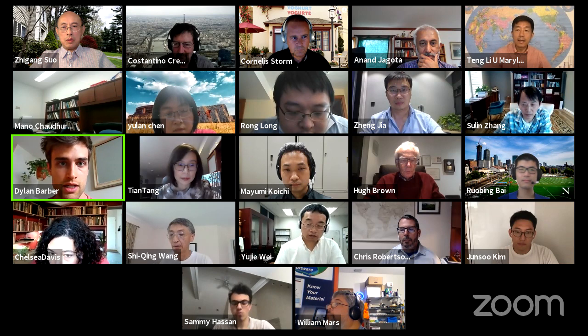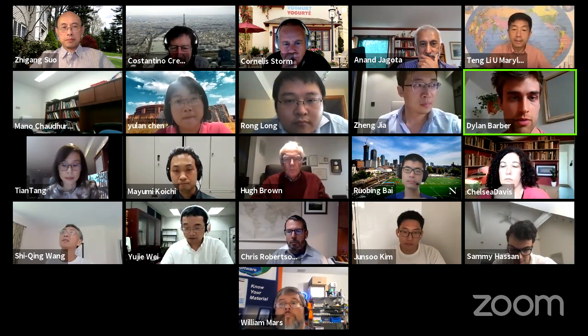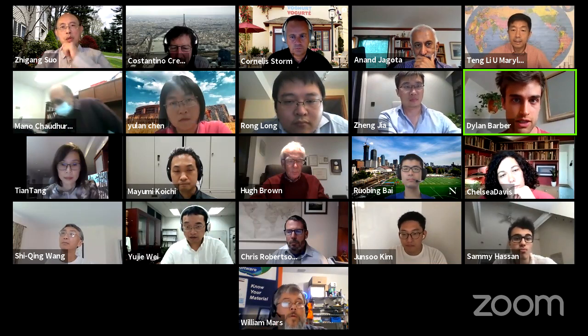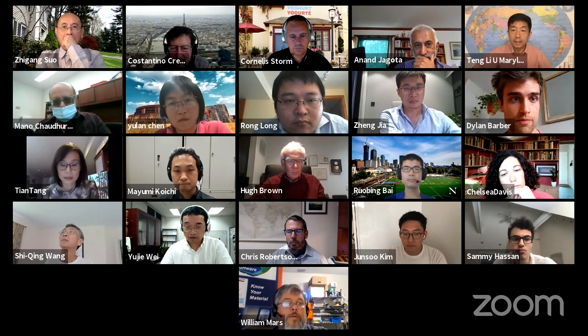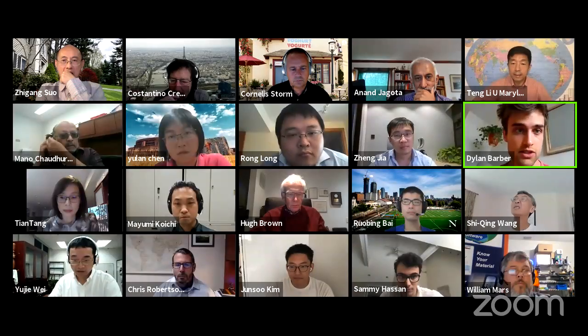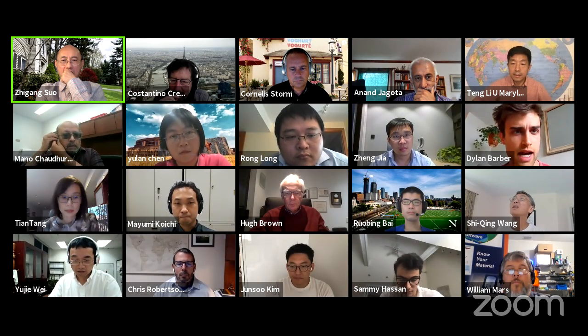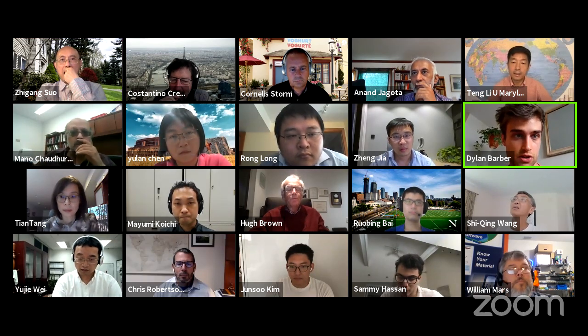Yep. Okay. So my question relates to the fascinating confocal fluorescence experiments that you ran, particularly with respect to temperature. At 25 degrees Celsius, you propagated the crack and you had a given fluorescence intensity. And then at 80 degrees Celsius, you ran the same experiment and the fluorescence intensity was diminished, much more attenuated. Obviously, mechanics play a significant role there. But also, has anybody run a control experiment on the mechanophore itself? Does it have a shift in fluorescence, or is there a change in the degradation mechanism as a function of temperature that may also contribute to that change in fluorescence?